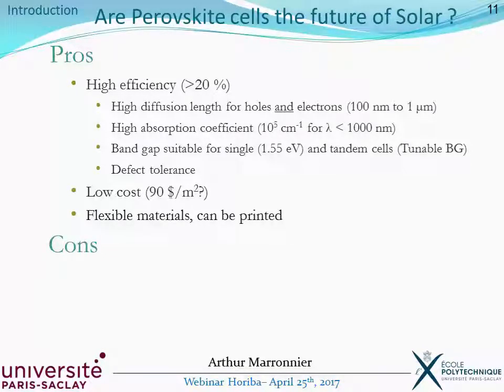And their band gap, which is around 1.55 eV for the methylammonium lead iodide perovskite, is suitable for a single cell, but can also be tuned by playing on the halide ions you use, to around 1.7 eV, for example, which is a perfect value to associate them in tandem cells with silicon solar cells. And they have a very good defect tolerance. So all these points, together with their low cost and their flexibility, the fact that they can be printed, they can be vaporized, they can be on any surface, makes them a very promising generation of solar cells.